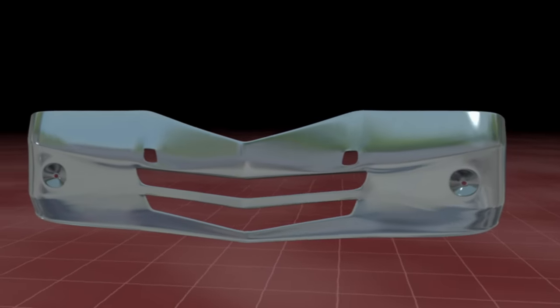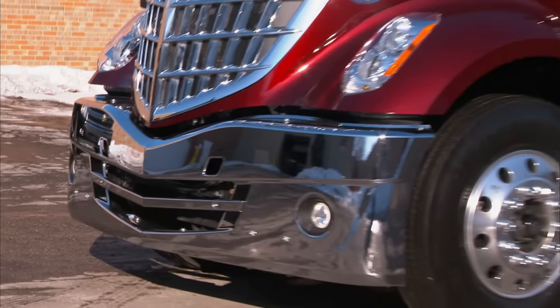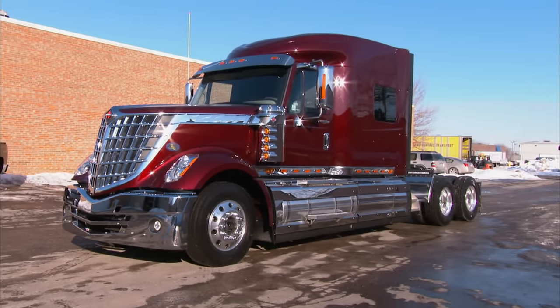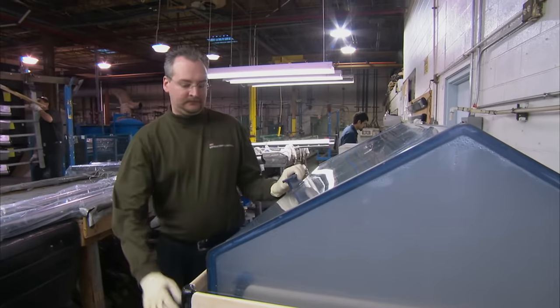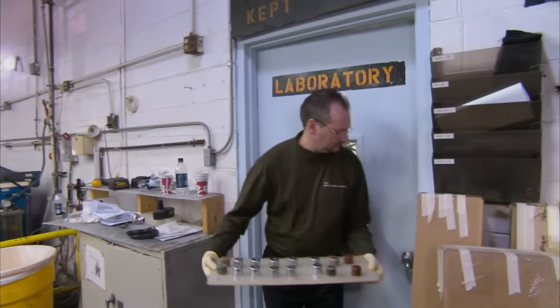While the aluminum bumper is just over an eighth of an inch thick, the nickel layer is only 15 ten-thousandths of an inch thick. And the outer chrome layer is just 15 millionths of an inch thick — more than 250 times thinner than a human hair. Even so, it adds sparkle and the utmost resistance to corrosion. To test this resistance, Arlington Plating technicians turn to a salt spray chamber, where placing parts for just eight hours simulates more than two years of real-life use.